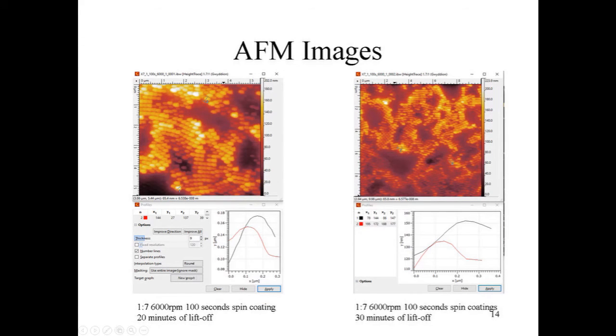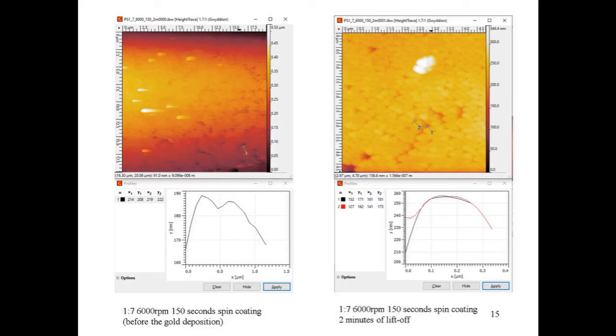After the deposition of the gold particles and lift-off for 20 to 30 minutes, we can see that there were still nanospheres on the surface that were not removed well with the current lift-off stage. Here are the steps from before the gold deposition to a total of 2 minutes of liftoff, respectively.